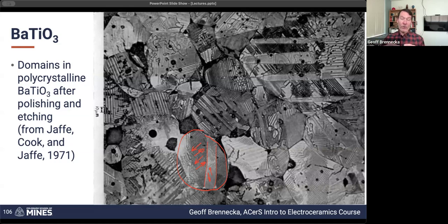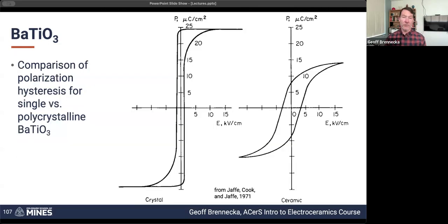And then within each grain, we also have these domain regions where even though the oxygen sublattice is completely coherent, we've got the cations that are displaced just a little bit in each direction to minimize the overall total free energy of the system. So the fun thing is, because this is ferroelectric, once we apply an electric field, we can get those domain walls to move and get the overall polarization of the sample to become non-zero, not averaged out to be zero everywhere.